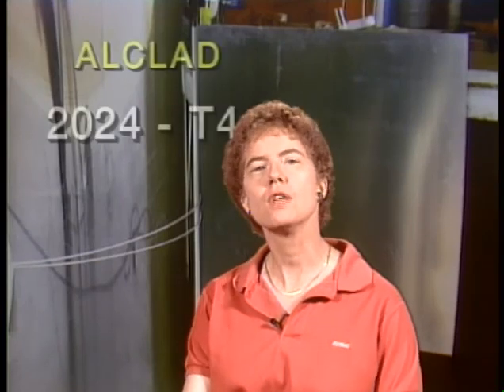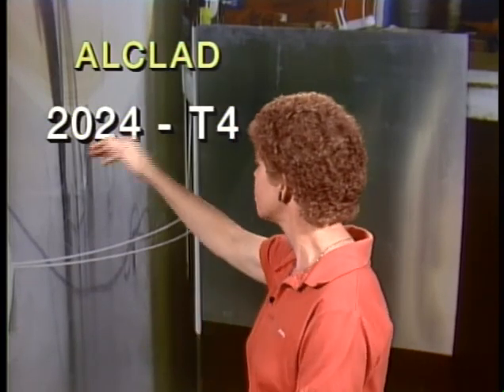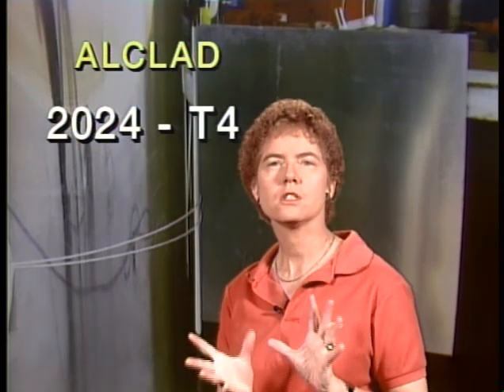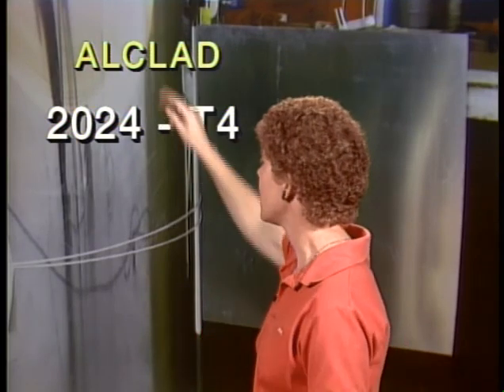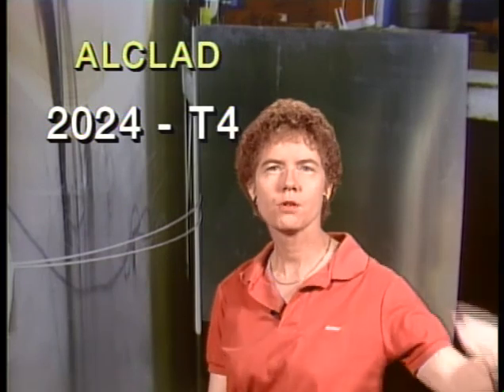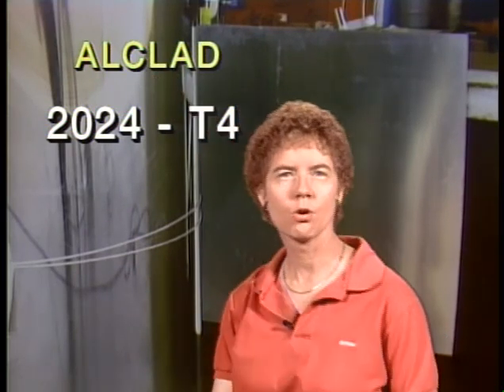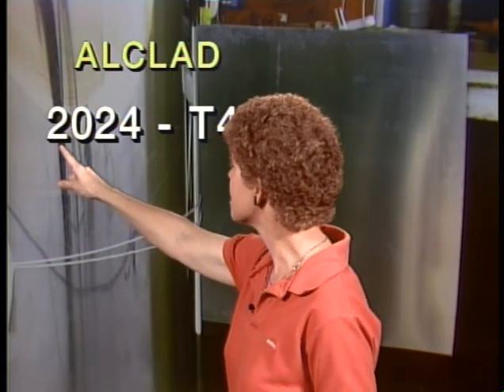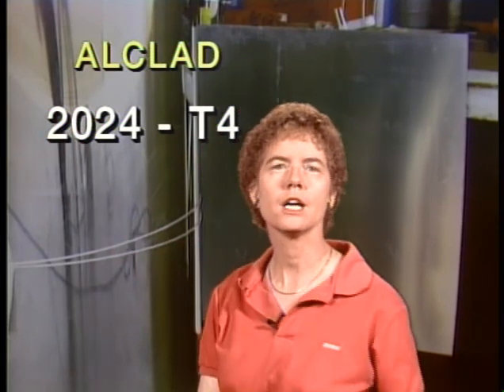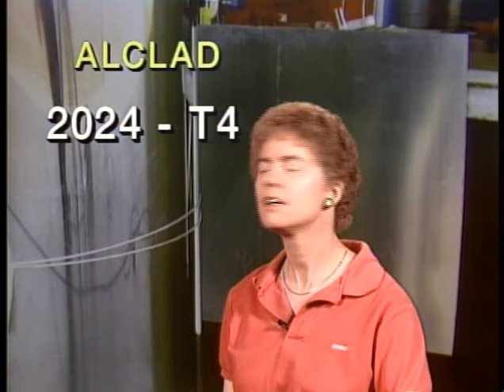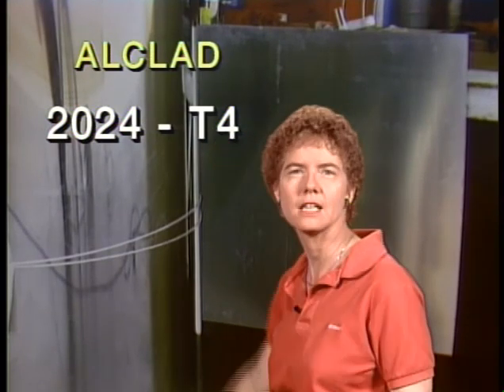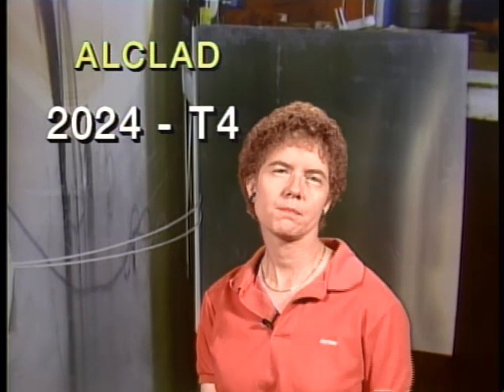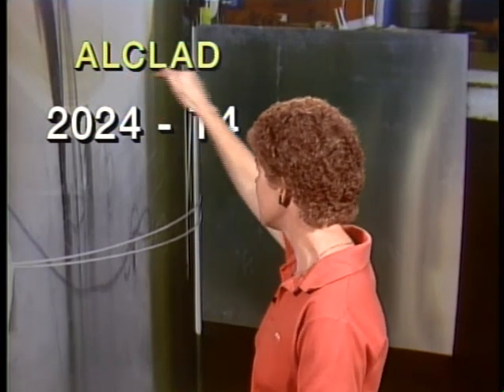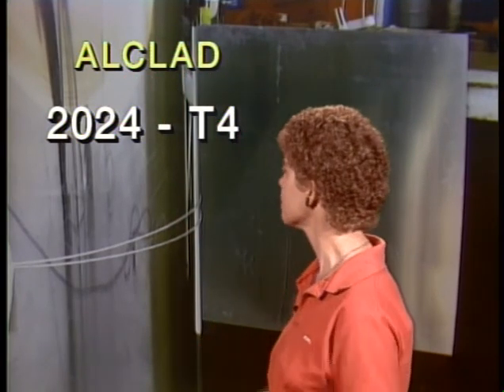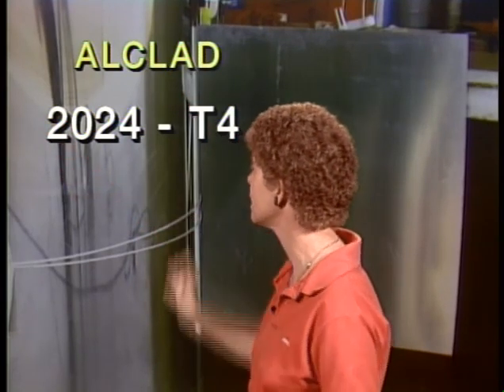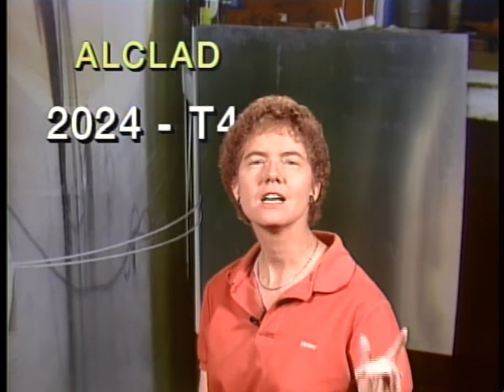So let's assume that they say to you that you have a material that is called alclad 2024-T4, and they want to know what exactly that means. Well, the alclad means that the surface of the material is pure aluminum, and it's got an aluminum alloy core. The 2024, the first digit is a 2, and that means that the major alloy is going to be what? It's going to be copper. It's a heat-treated aluminum alloy because it's got a -T4 at the end of it. The -T4 indicates that that particular metal has been heat-treated. So you've got alclad, you've got commercially pure aluminum on the surface, you've got an aluminum alloy core, and the major alloy is copper, and the -T4 means that it has been heat-treated.